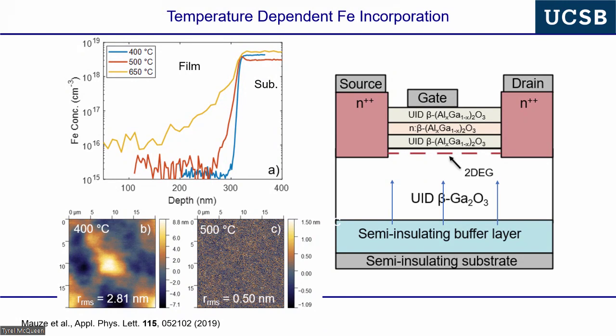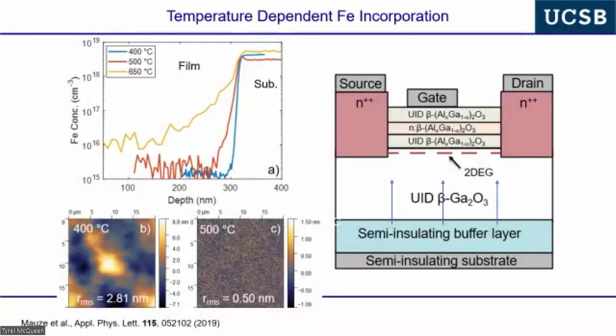And if you ignore these profiles, if you grow, and this is a little bit on the cold side, but still at sort of typical MBE temperatures, you'll get this long tail of iron from the iron-doped substrate into the film. And in the field, this was always attributed to diffusion of iron. But temperatures are actually quite low if you look at this for iron diffusion. And then you notice if you grow colder and colder, you have less, and you say that's still consistent with diffusion because you're growing colder and colder.